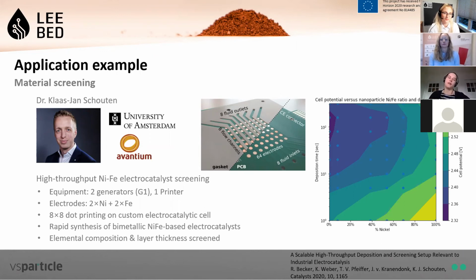And we have deposited the nickel iron electrode layer on top of this. And for that, we use two generators and one printer, so the prototype of the printer. And one generator was equipped with nickel, the other generator was equipped with iron. And by changing the power of the spark, we could change the ratio of nickel to iron in the 8 rows. And we also varied the deposition time in the 8 columns. So we had a nice array of varying input parameters, and then we send it back, and they could quickly get to their results.